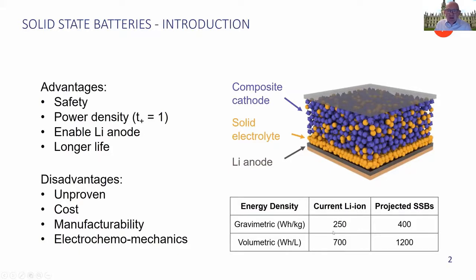To give a flavor of the performance advances that might be possible: in terms of energy density, we are currently around 250 Wh/kg and 700 Wh/L with a lithium-ion battery, and one can project around 400 Wh/kg or higher and 1200 Wh/L for solid-state.